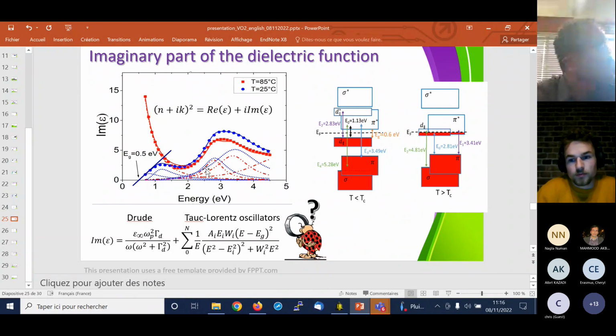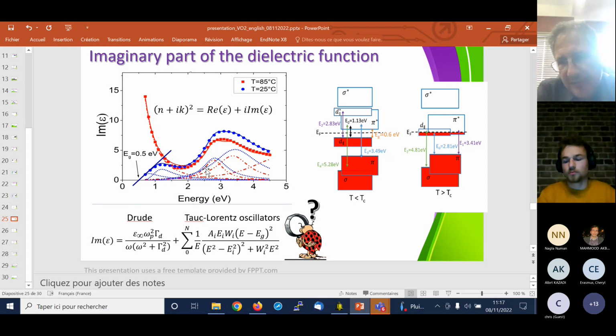Yeah, you have to be careful with the point by point, because it depends on the initial point where you start the measurement. In fact, what we did, we took the point from the Lorentz fit, and after we did the point by point. And there is another possible problem, the roughness of the sample. Because in the point-by-point model, we did not take into account the roughness, but we checked that this is not a problem before doing the analysis.